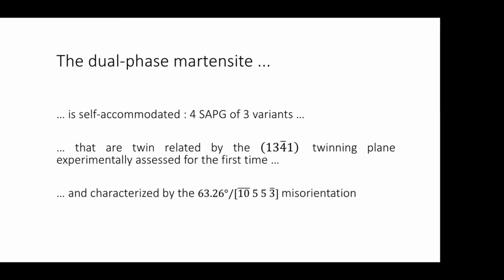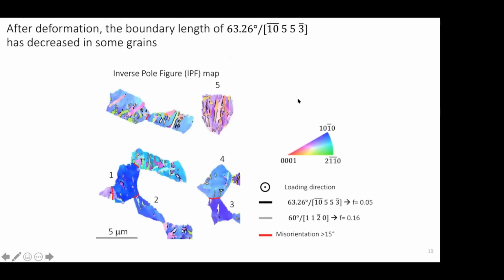So the idea is to have a look at the martensite after deformation to try to understand its mechanical behavior. To do so, we did exactly the same thing, starting with an EBSD map of the martensite after deformation. The first thing that we can say is that the 2 misorientations, the one at 63 degrees and the one at 60, still remain after deformation. But the fraction of the one at 63 degrees has greatly decreased, because you can see we have a fraction of 0.05 instead of 0.4 before deformation. And by contrast, the one at 60 degrees remains in quite equal proportion.